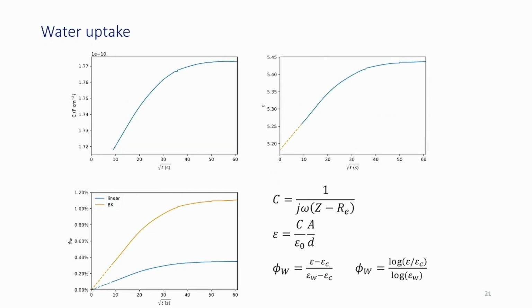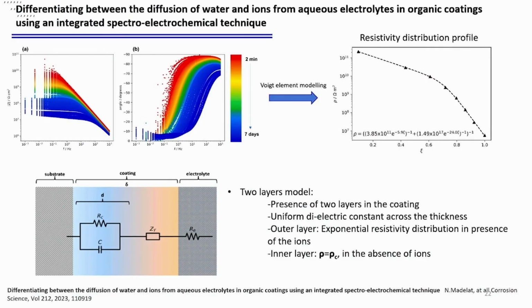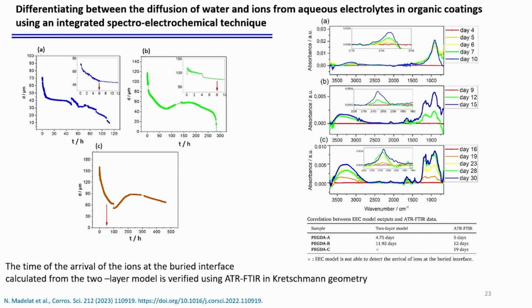Then, of course, like was done in the literature, we can calculate the water uptake from the dielectric changes. And then, in France, they have already published the change of the resistivity. So we have looked at what this change in resistivity could mean. And out of that, we came up with a mechanism to measure the ion transport through the coatings by this type of fitting. So in fact, this is a resistivity profile as a function of time, which shows you the ingress of the ions in the coating.